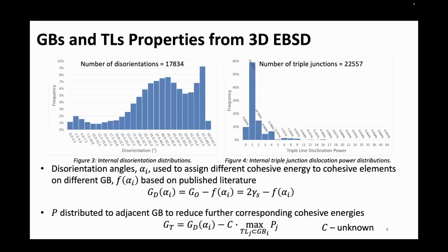With this information, we developed three methods to calculate the grain boundary energies. The first method is based on two times the surface energy of nickel alloy, which is 2 gamma S, and this method is denoted as G0. For this method, we consider all the grain boundaries to have the same energy, so it's a baseline approach. Our second method is to assign different cohesive energy based on the disorientation of the grain boundary, based on the existing literature. With this method, we can account for the effect of disorientation of the grain boundaries.